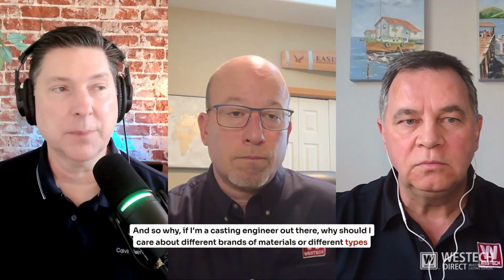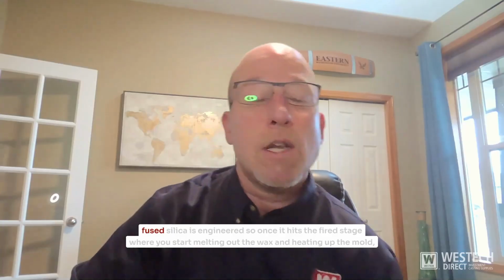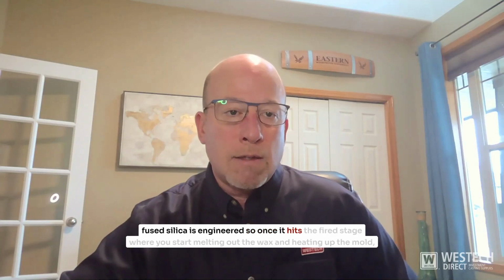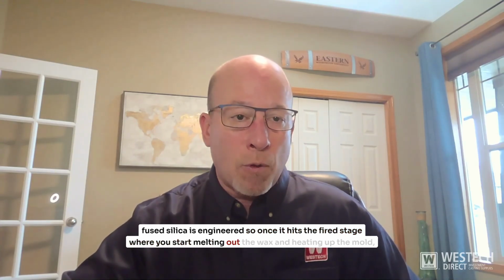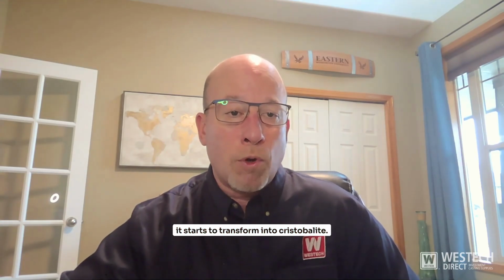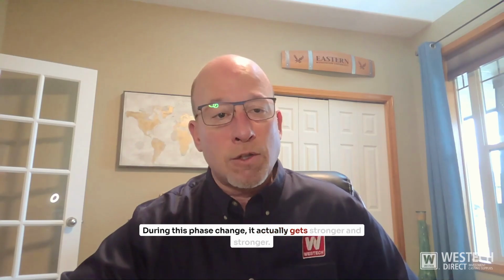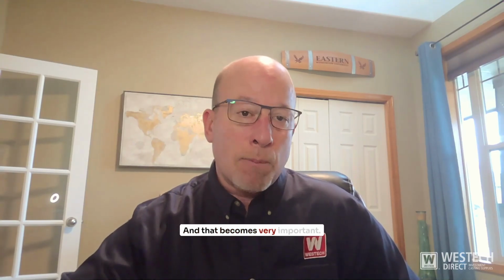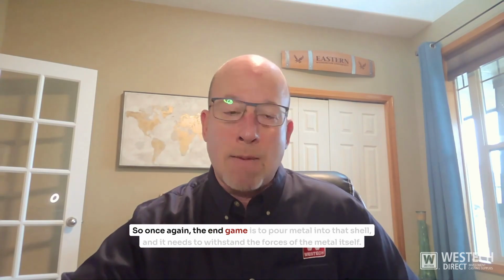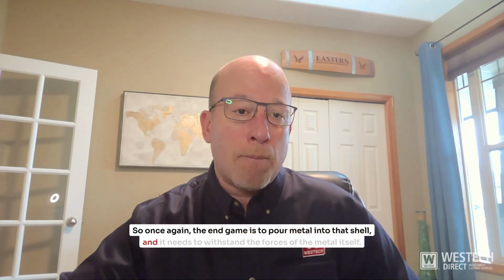And so why, if I'm a casting engineer out there, why should I care about different brands of materials or different types of materials? Like, I get the size of the flour that I want and I'm done, right? Fused silica is engineered, so once it hits the fired stage where you start melting out the wax and heating up the mold, it starts to transform into cristobalite. During this phase change, it actually gets stronger and stronger, and that becomes very important. So once again, the end game is to pour metal into that shell, and it needs to withstand the forces of the metal itself. So strength becomes very important.